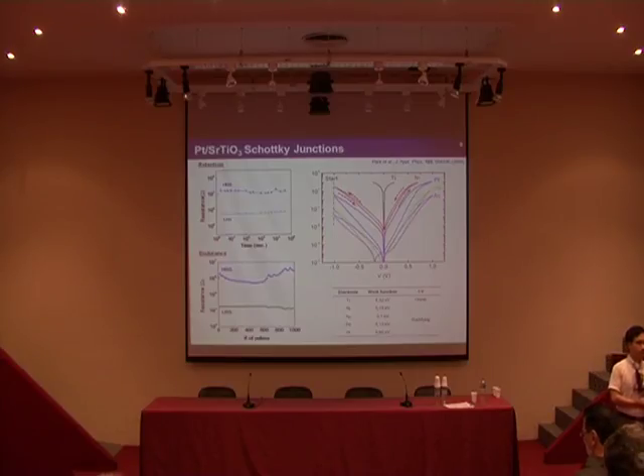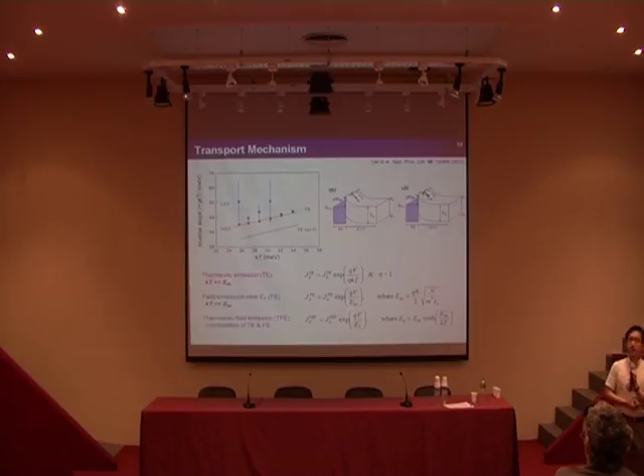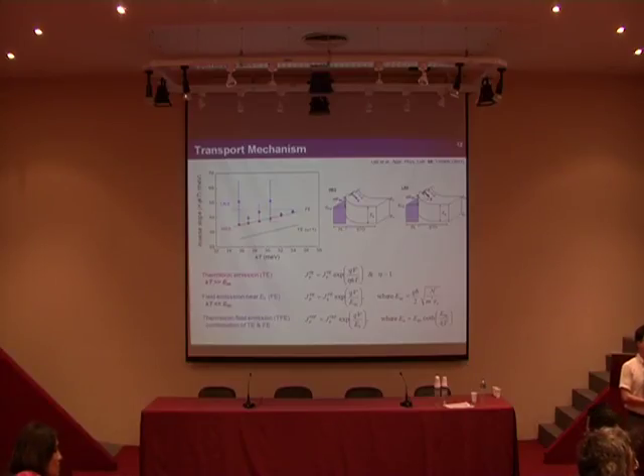So you showed in your model, partially, the local potential profile and the Schottky barrier decrease. But I think your results can be explained by another model - locally, the Schottky barrier width becomes thinner. In this case, the internal photoemission also does not depend on the resistance state.